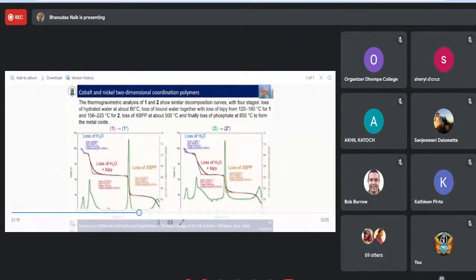And finally, you have basically nothing happening between 250 and 500 degrees. You can see that here. There's basically nothing happening. And so this is why we can heat up to 300 degrees and only the BP and the water will leave, and your bisphosphonate ligand only decomposes above 500 degrees. So it's an extremely stable compound. And this forms a phosphate. And then when you get close to 900 degrees, the phosphate decomposes and you're left with metal oxides at the very end. So they're basically the same. You can see the percent of the masses here corresponding more or less to the presumed losses.